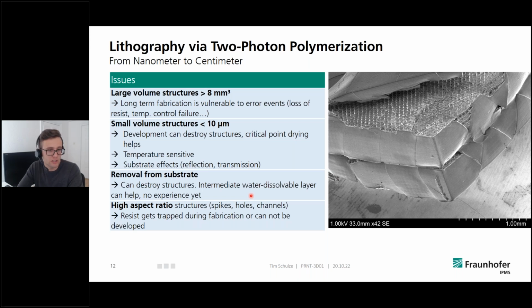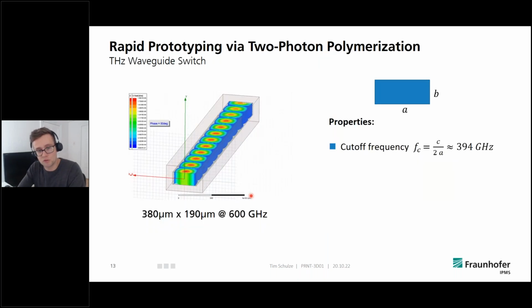With large structures, usually no problem. Even I picked up little structures with a tweezer very easily, but small structures can also be quite challenging. And usually if you have high aspect ratio structures, for instance, little holes in your structures, it could sometimes be possible that you are not really able to wash the resist out of this. And yeah, just a lot of trying and gaining experience is necessary to be very flexible in the things you are doing. And last but not least, I want to give you an example of the things I personally have been doing a lot with the printing system, and where I was super glad to have such technology at hand.